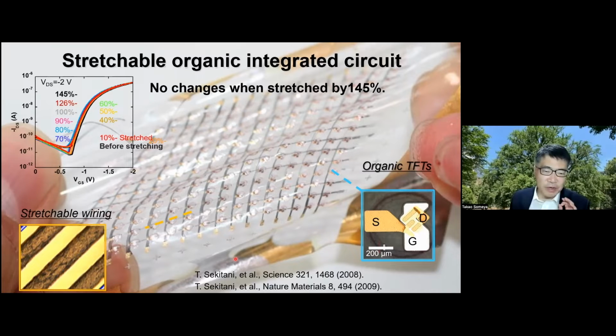Our approach is quite straightforward. First, we put a 2-dimensional array of rigid islands, which are embedded in rubber substrate. And then we make the organic transistors by printing. And finally, source, drain, and gate are connected by utilizing printable elastic conductors. In that way, when we stretch our devices, all the strains are accommodated by changing the length of the wires. So we can achieve stretchability over 145% without causing any mechanical defect.